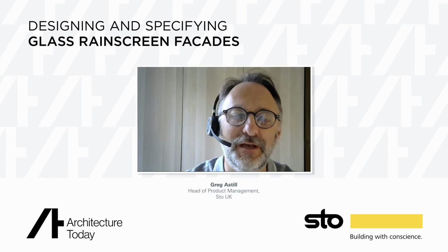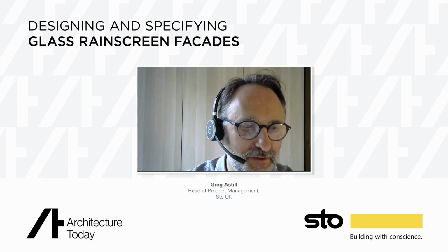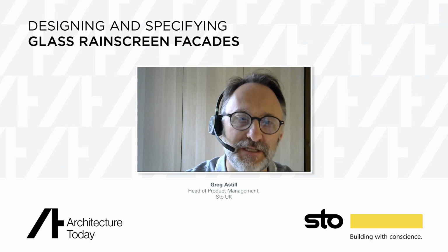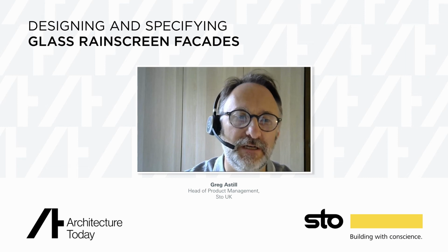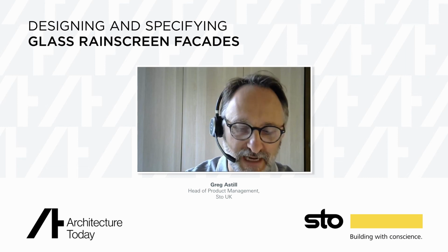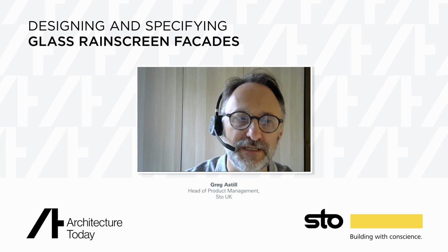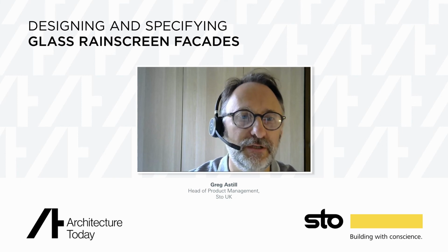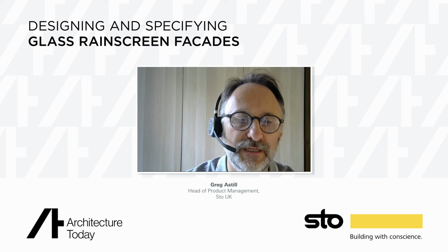I'd just add that with the low iron glass, as Darren said, you would typically use it on lighter colours, whites or lighter pastels. By the time you're getting into the heavier, more intense colour shades, that greenish hue tends to disappear, or it can't be distinguished anymore. So you wouldn't need to do that.